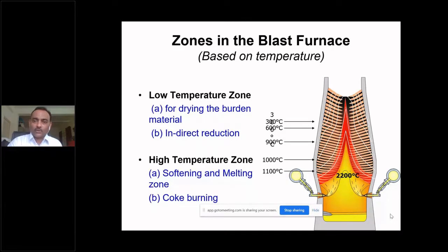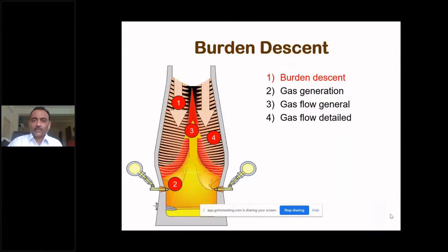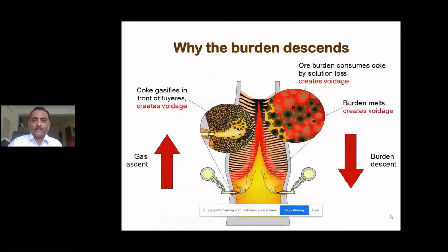We charge raw material from the top, and from the lower level, we send hot air. Because of this hot air, coke burns and the melting happens in the furnace. These are the different zones in the furnace. Quite naturally, gases go upward and raw materials move downward. Because when melting happens in front of the tuyere, we remove the hot metal and slag from the furnace. By this diagram, it's clear.